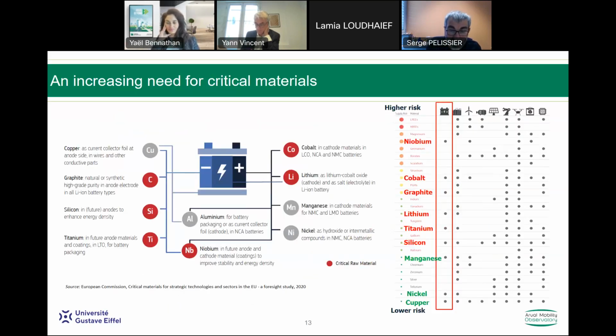If you look at the different materials you can find in a battery, which are shown here: graphite, silicon, titanium, niobium, manganese, lithium, and so on. Some of them are part of the critical materials. But lithium is not the most critical, because in the list of the critical materials, you can see that the higher risk is expected for niobium, cobalt, and graphite, but not especially for lithium, which may be a critical material, but not so high on the scale.